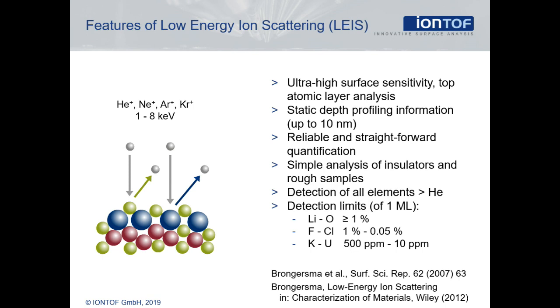Since the noble gas ions have a strong driving force for neutralization, only a fraction is still ionized after the collision and can be detected. This is the reason for the ultimate surface sensitivity, which is the main feature of LEIS.